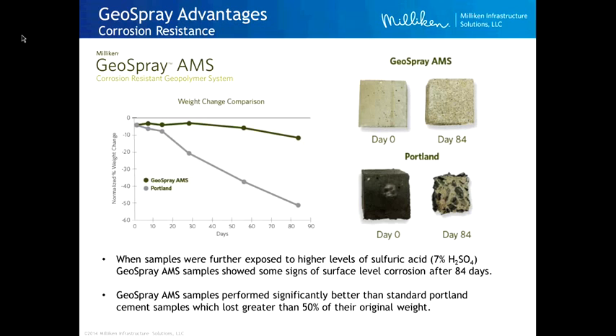And this is a test we recently did. We took some cubes, Geospray at the top, Portland cement at the bottom, and following the protocols in an ASTM test, which the test is not listed on here, but basically it's an 84-day test. We put them in a 7% sulfuric acid concentration, which is a pH of about 0.9, so it's very acidic. And you can see after 84 days, we just had some minor discoloration and surface deterioration. With the Portland cement, we had over 50% material loss, and basically we have the aggregate left and a little bit of binder holding it together.